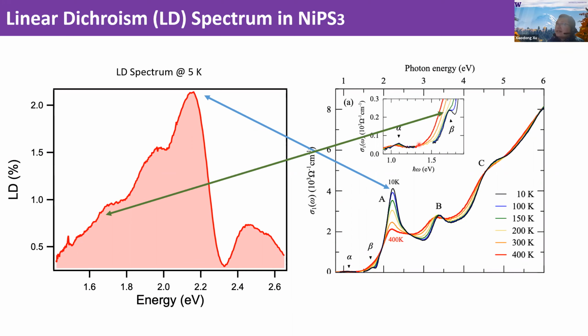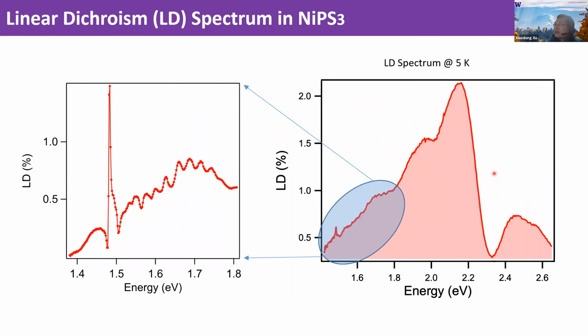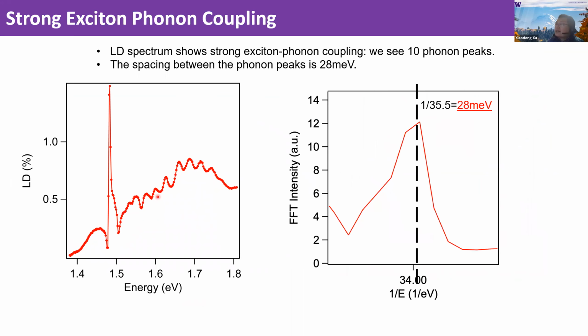But in our LD spectra, if I zoom in on this little shoulder, now I see many wiggles appear, a lot of wiggles. And when I saw these wiggles, the first response was, well, okay, there could be exciton magnon coupling effects. So we did a Fourier transform, and we found that the period of these wiggles is 28 millieV. So it's not magnon, because the magnon in nickel phosphorus trisulfide is actually 5.5 millieV. So this is not magnon.